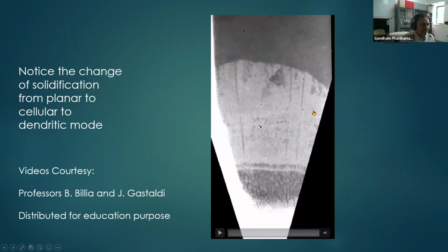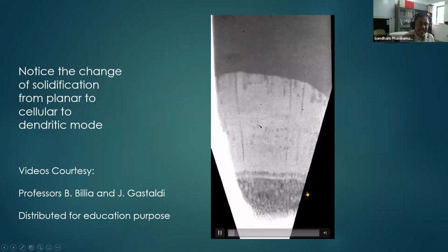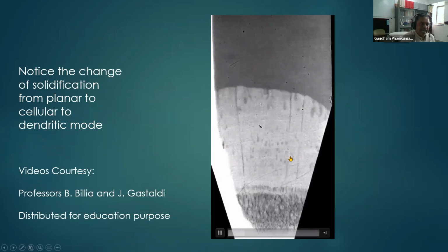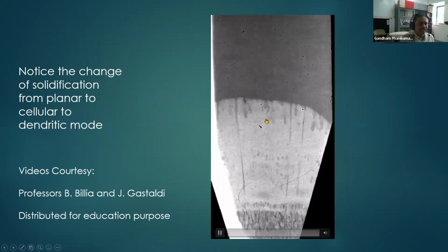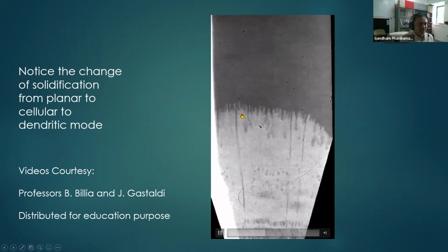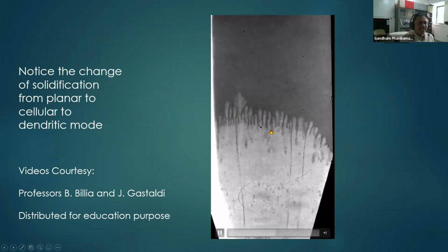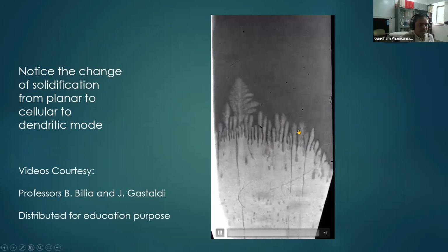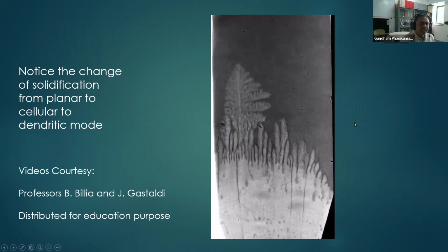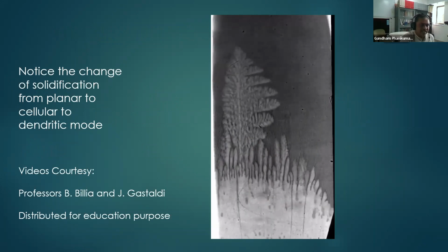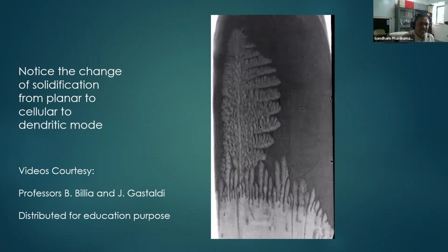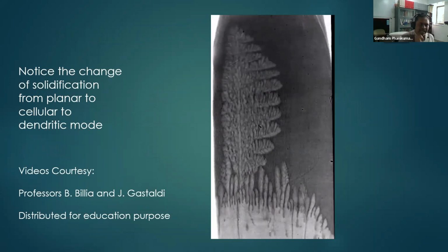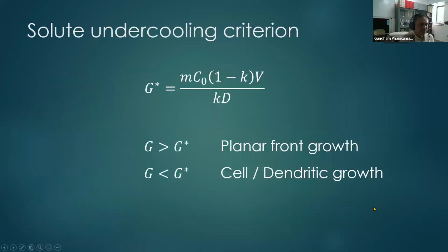That transition from planar to cellular is something that can be seen in metallic materials using synchrotron. This is a video that shows you that the planar growth of grains can become cellular, and then those cells can become dendrites. So this is a live demonstration of how the transition happens. And this is actually what is happening in additive manufacturing when you are moving a laser, except that it is happening very fast and at a very small scale. But the physics is exactly the same.